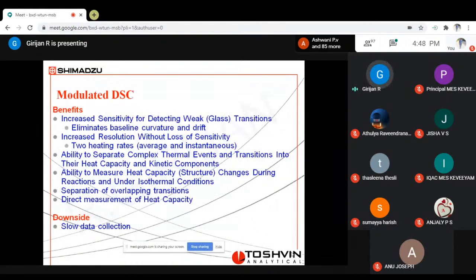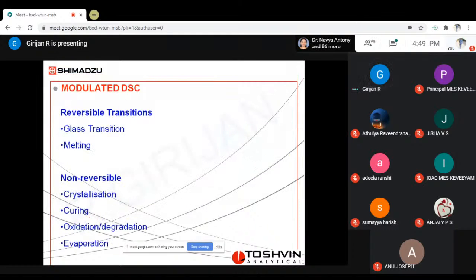And direct measurement of heat capacity. Heat capacity also can be measured by DSC, but it is difficult. You have to carry out three different experiments to find out the heat capacity of a compound using normal DSC. But in MDSC, in just one experiment, you can directly find out the heat capacity of the compound with maximum efficiency. And the only downside of the technique is that it is a slow mechanism, with slow data collection. That's the only downside.